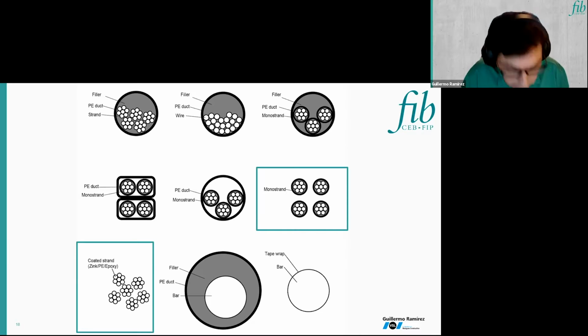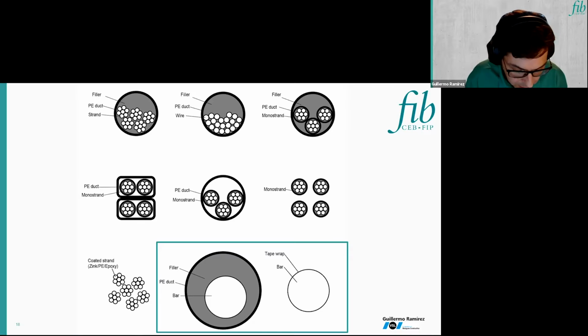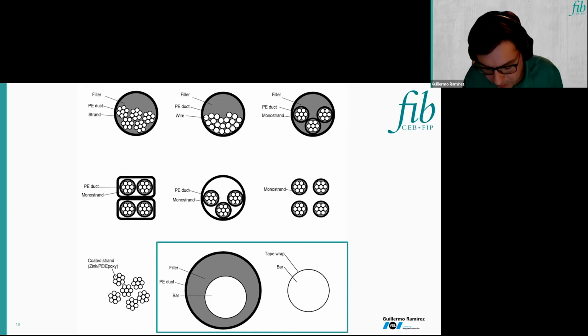Finalizing this review of strand applications, we will see also examples of single strands, either monostrands or epoxy coated. And we also find tendons with post-tensioning bars. These bars are commonly found inside PE pipe with filler, again, either grout or soft fillers, or wrapped with a tape system. You see there's quite a big variety as opposed to internal tendons. We do not typically have all these combinations.